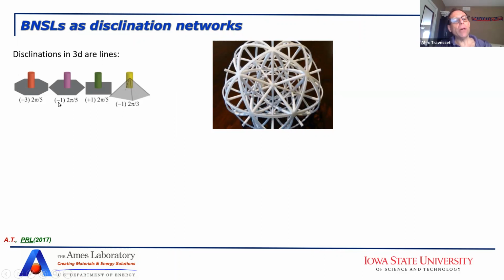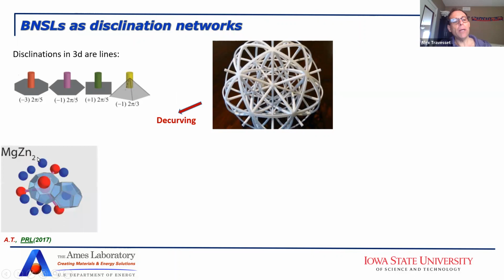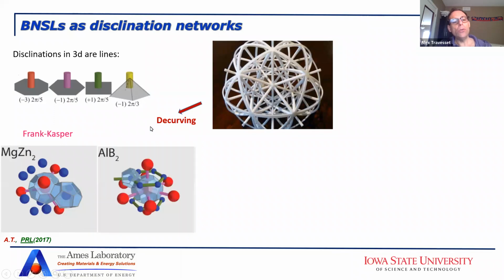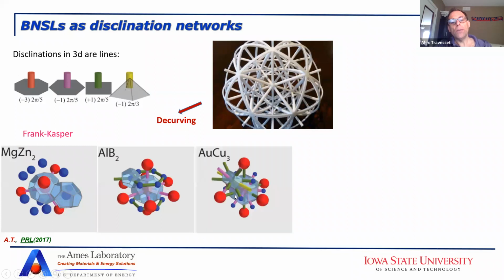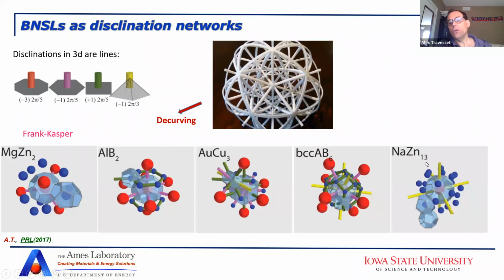And then if you just use the -1 2π/5 disclination, you can decurve the 335 polytope, and you get the magnesium zinc 2, and this is what is called the Frank-Casper phase. But we don't have to restrict ourselves to just this type of disclinations. We can also use the other ones. And when you do, you get the aluminum boron 2. Here you have, this is the disclination network, the gold copper 3, the BCC AB6, or the sodium zinc 13, which consists only of 2π/3 disclinations.